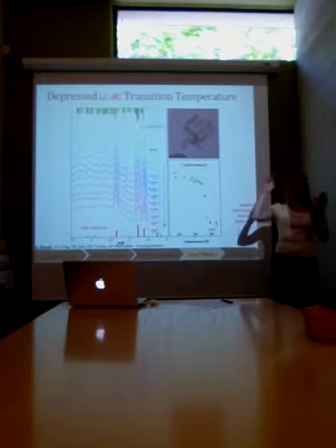And the reason for that is that as we transition from low to high chalcocite, the very complex ordering of those copper ions becomes amorphous. And this means that we're having a reduction in the electron mobility in our film. It's more difficult for electrons to move in an amorphous material than in a crystalline material. So low chalcocite had relatively high carrier mobility, whereas high chalcocite is going to have relatively low carrier mobility. Additionally, the high chalcocite phase has a lot of ionic mobility because these copper ions are very amorphous. It has high ionic mobility. So neither of these things are good for a photovoltaic cell.